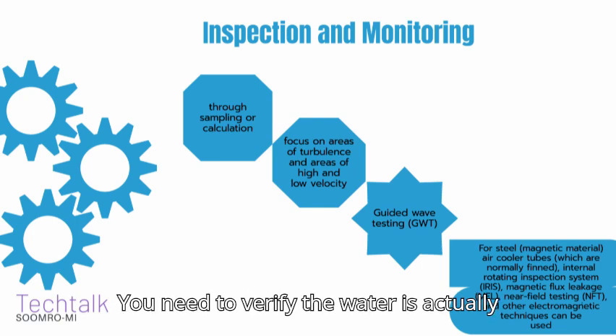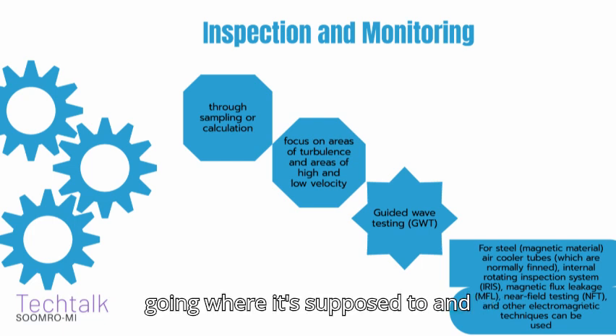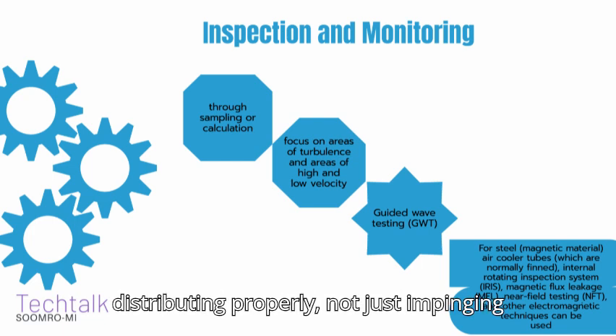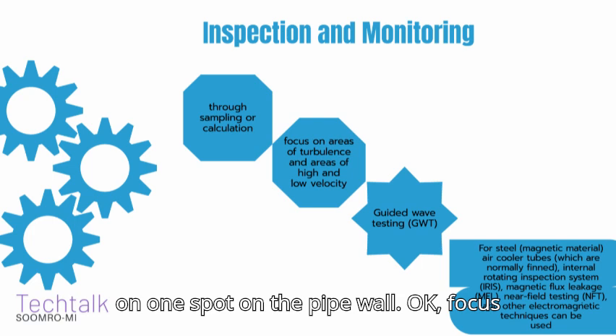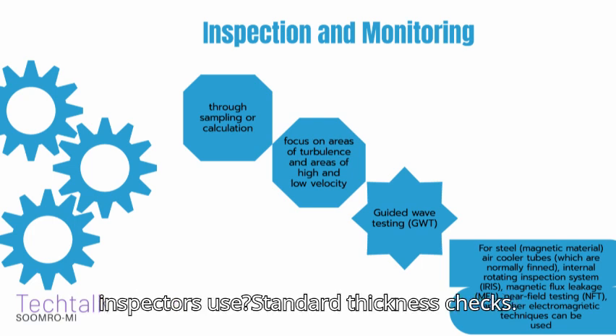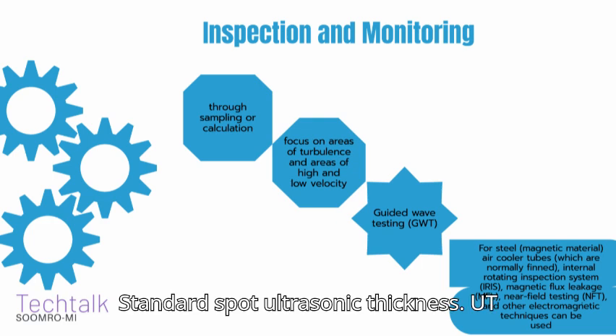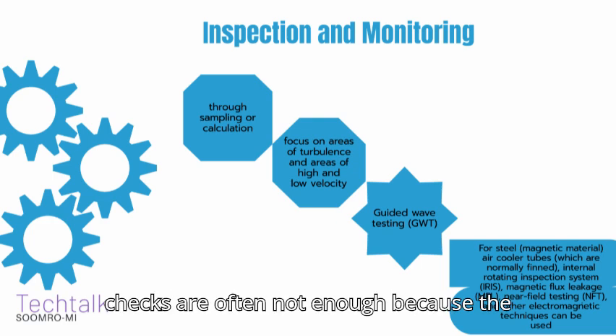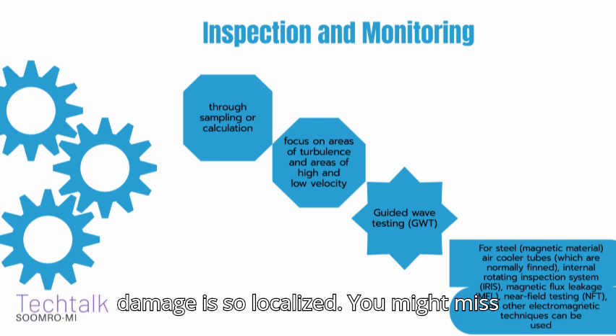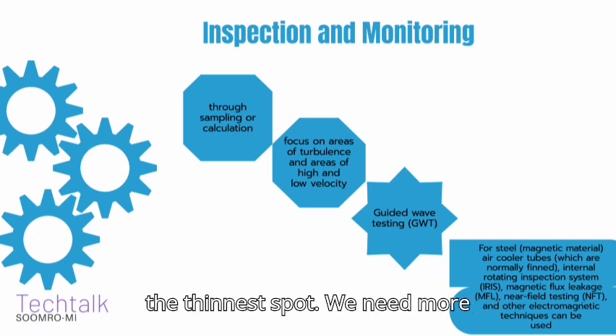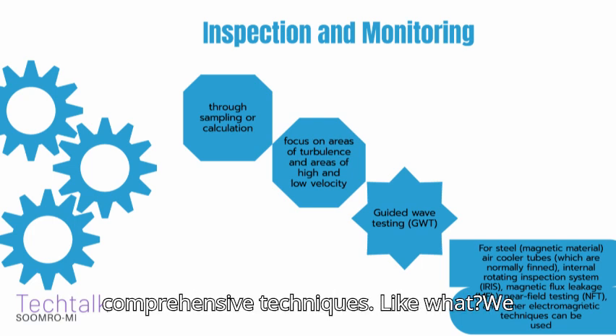You need to verify the water is actually going where it's supposed to and distributing properly, not just impinging on one spot on the pipe wall. Okay, focus on the known trouble spots. What tools do inspectors use? Standard spot ultrasonic thickness, UT checks, are often not enough because the damage is so localized. You might miss the thinnest spot. We need more comprehensive techniques.